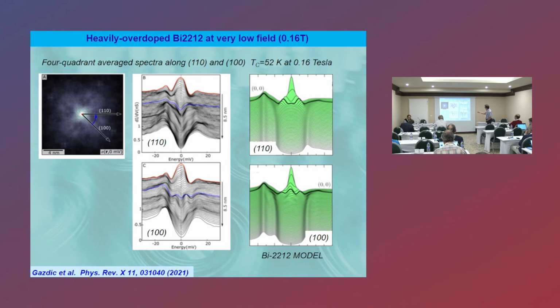So again, we check the directionality, which is similar to the one I showed you before, along the nodal or not nodal, anti-nodal direction. And interestingly, we also checked whether by removing the vortex and just putting the field to 0 at the exact same position, so it's atomically the same position in both cases, when the vortex disappears, we recover the expected spectroscopic signature of the superconducting state. So the peak we see in the vortex is for sure not linked to any doping, impurity or whatever defect which could produce this behavior.